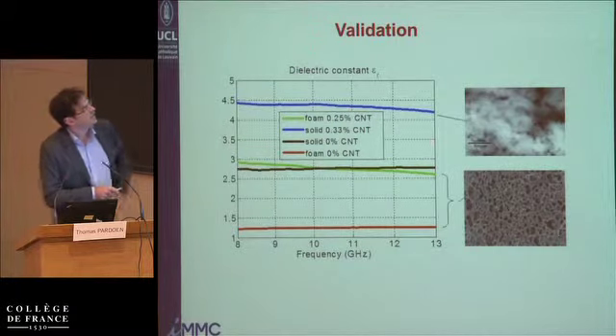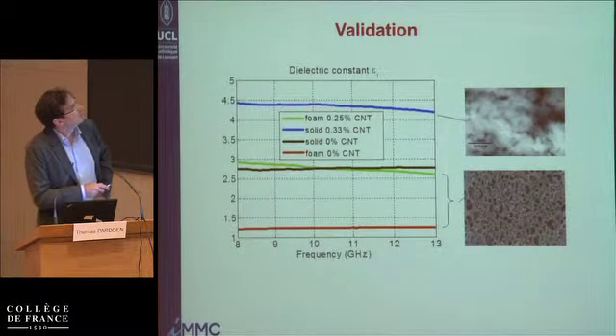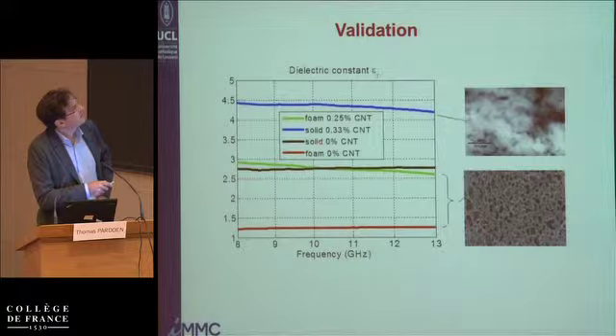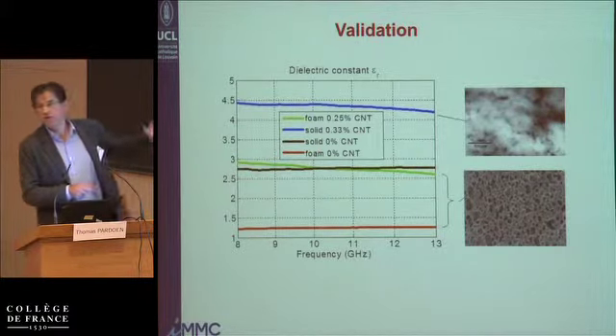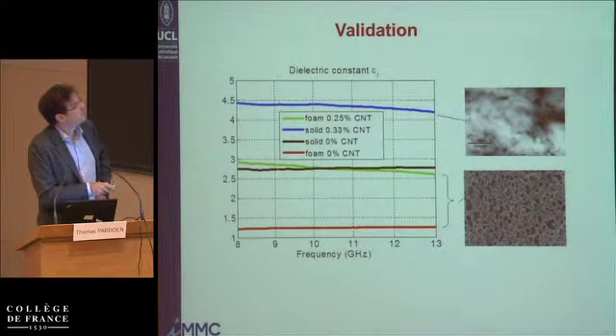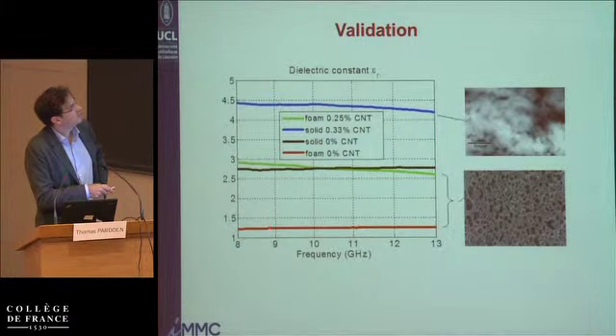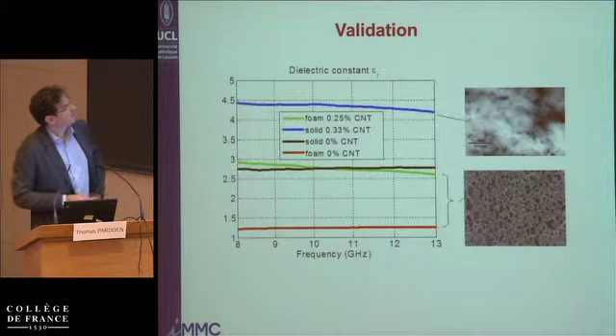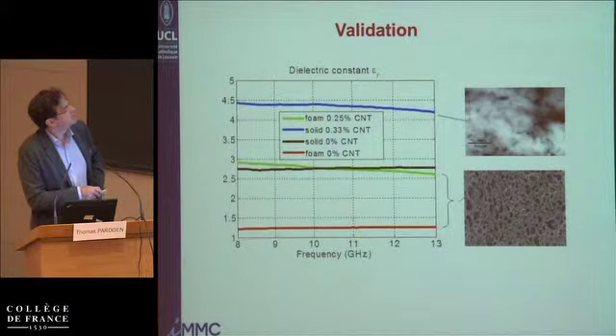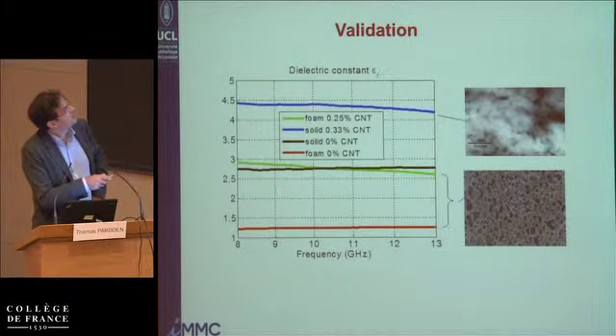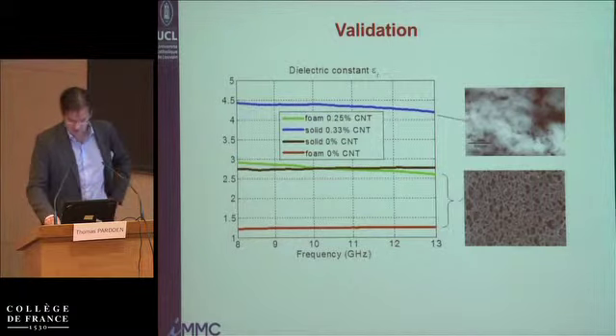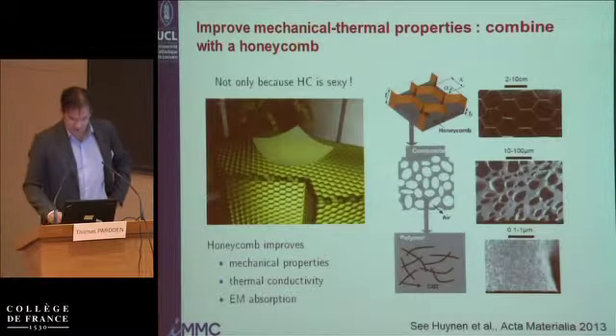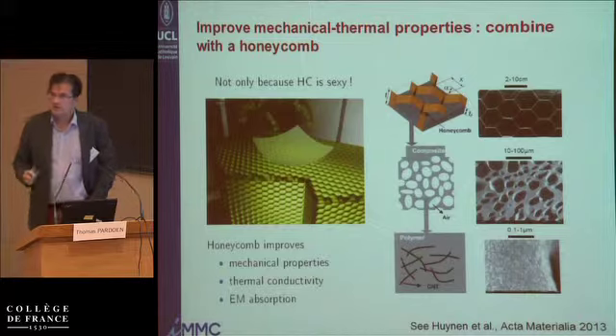I have examples here where you have in black a solid material with carbon nanotubes, so not the right conductivity, and then you make a foam. You see that the dielectric constant is decreasing in the entire frequency range. Here it's in gigahertz, and you see now for the solid material with carbon nanotubes the drop when you foam it in terms of dielectric constant.